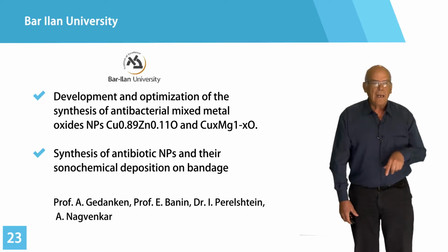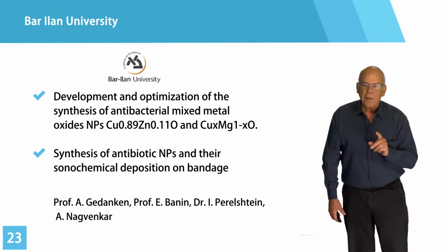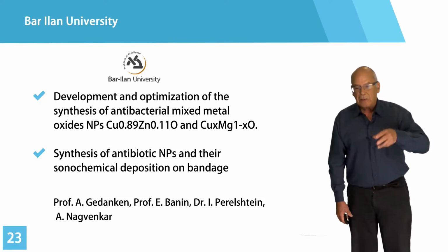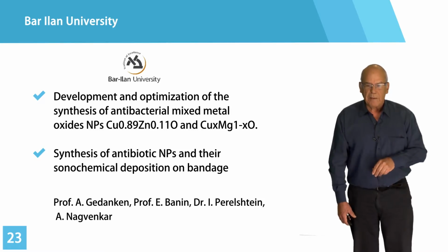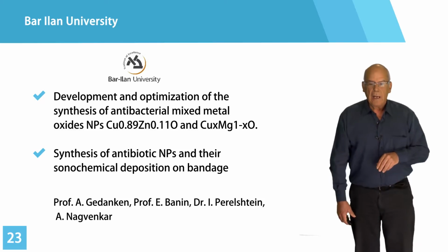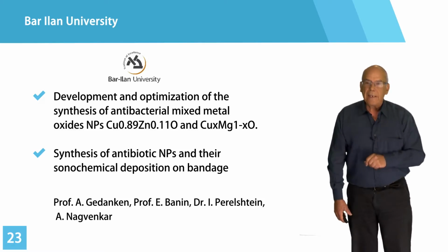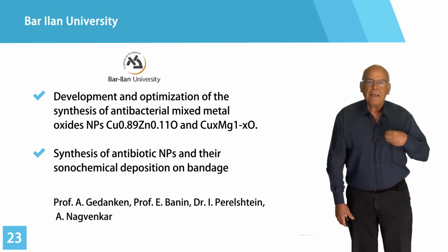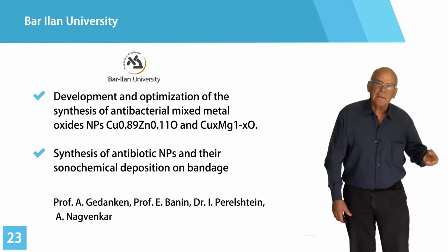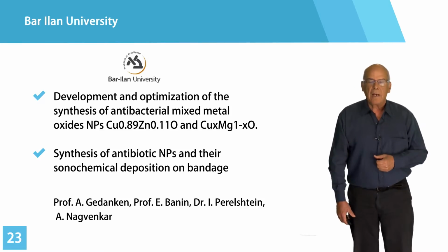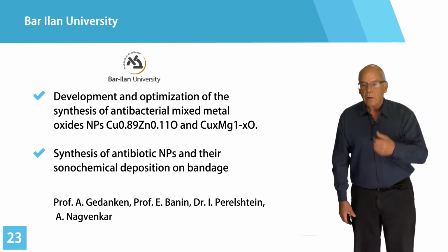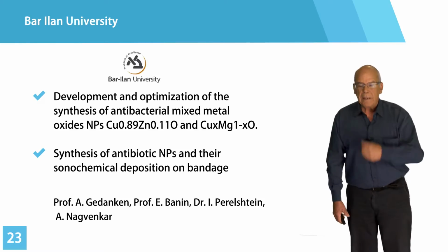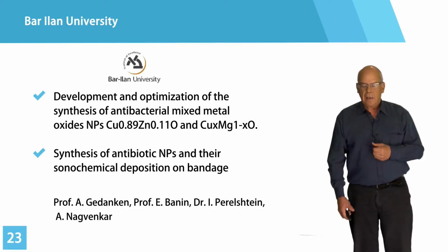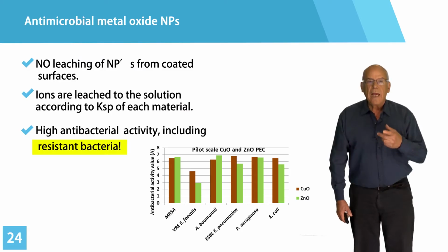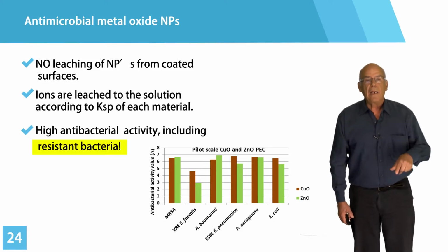Now, the case of most interest to us is a new material that we have developed and suggested to extend the development of, and they are called mixed metal oxide. As you see here, copper 0.89, zinc 0.11 oxide is a material that has a capability to kill bacteria 10,000 times better than either zinc oxide or copper oxide. Very promising material. And for example, we want to synthesize in parallel a new one, copper magnesium oxide. And this involves, in the case here, the most promising material to kill resistant bacteria.